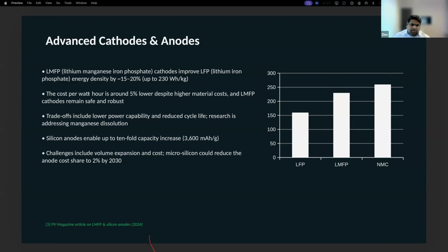LMFP remains cobalt free. As I told you before, cobalt is geopolitically a material which they're trying to reduce in the overall chemistry, and LMFP retains the safety and long cycle life of LFP. However, it suffers from lower power capability and manganese dissolution, which can reduce the cycle life compared to lithium-ion. So researchers are currently working on developing coatings, dopants, and electrolyte additives to mitigate the aforementioned issues.